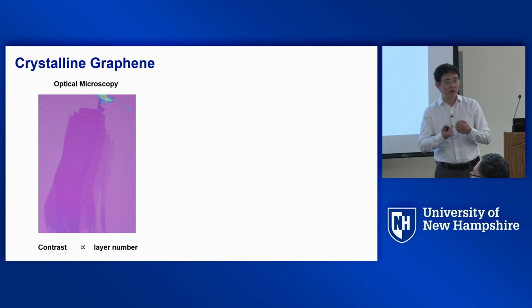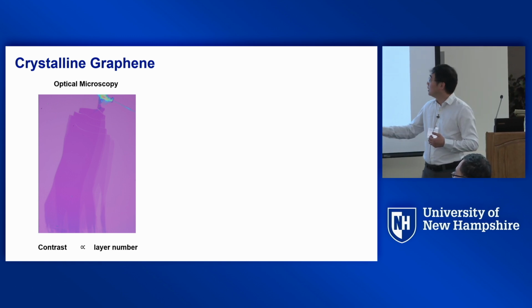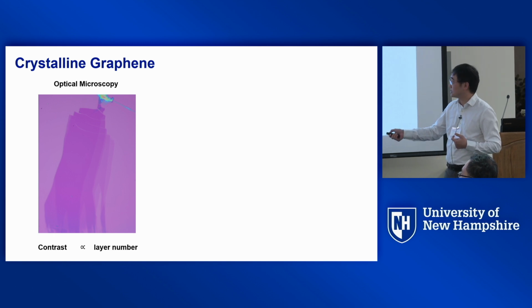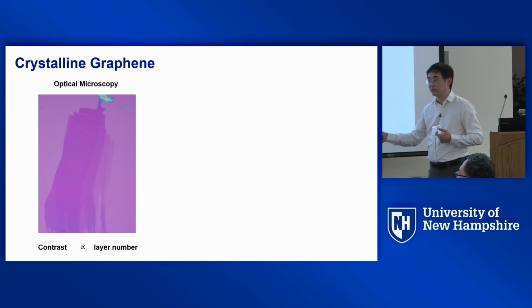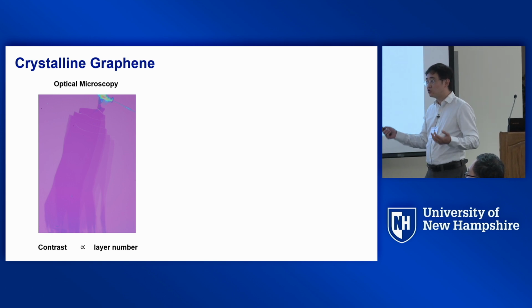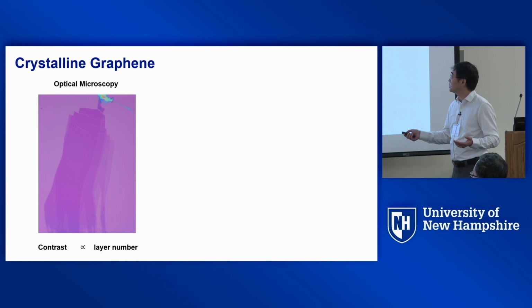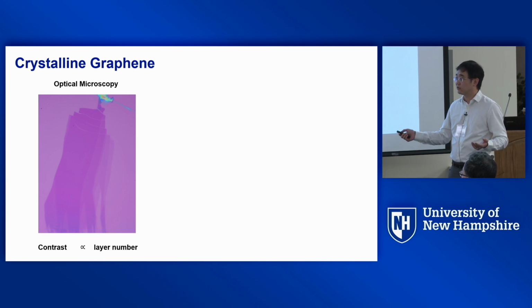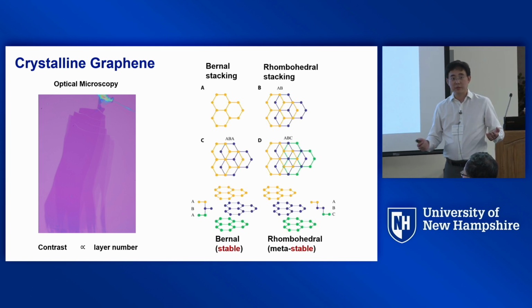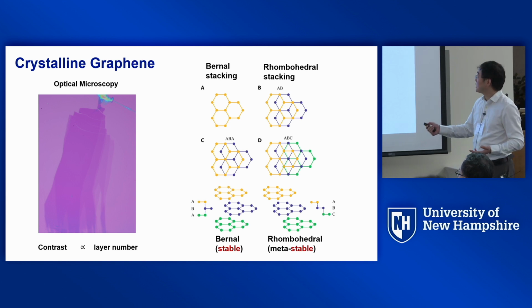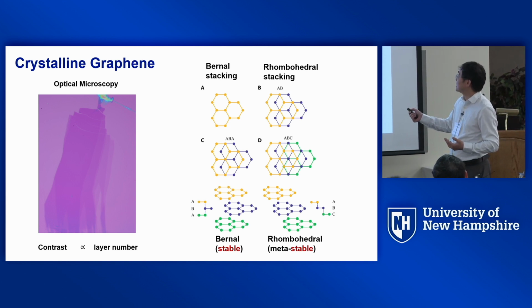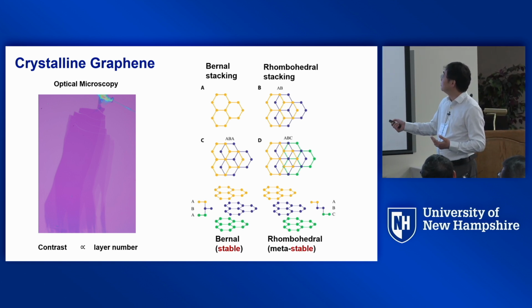If you exfoliate graphite and get a few-layer-thick graphene on the silicon oxide on silicon substrate, you can tell that there are regions with different contrasts. And that's simply proportional to the number of carbon layers you have there. But it turns out the structure of graphite or graphene multilayers is richer than just having different layer numbers. There could also be different stacking orders. For example, these are the two leading stacking orders when you have more than 3 layers.